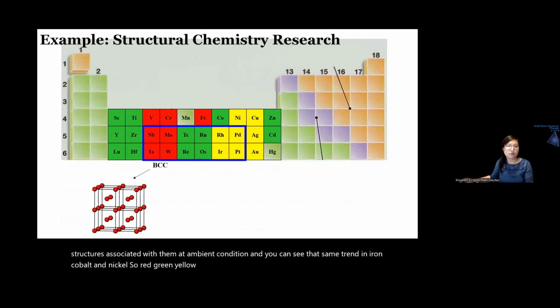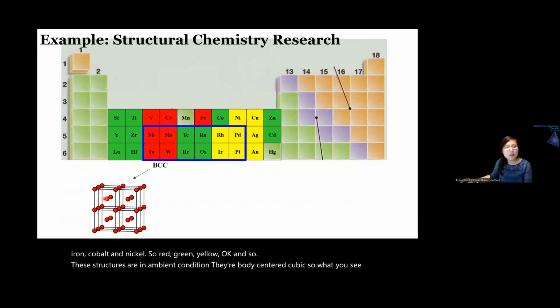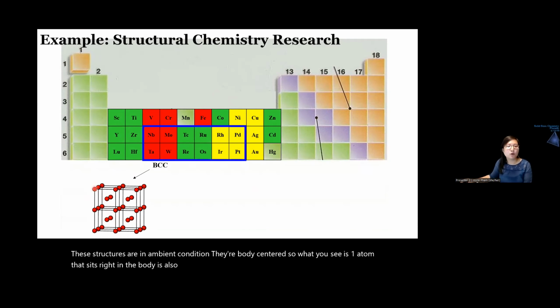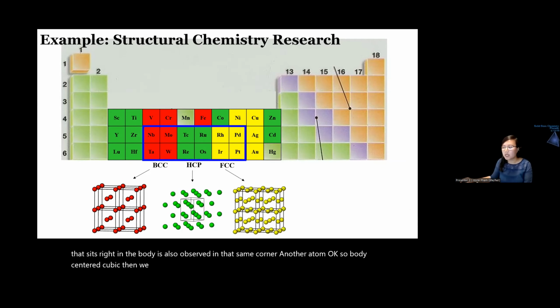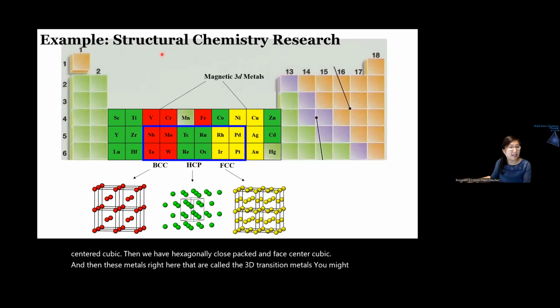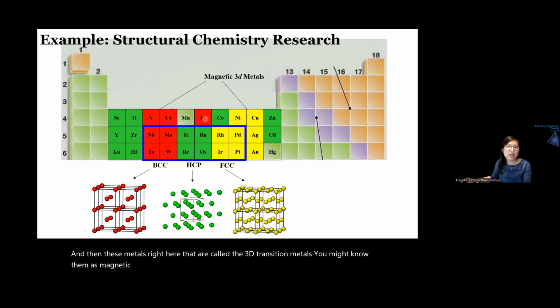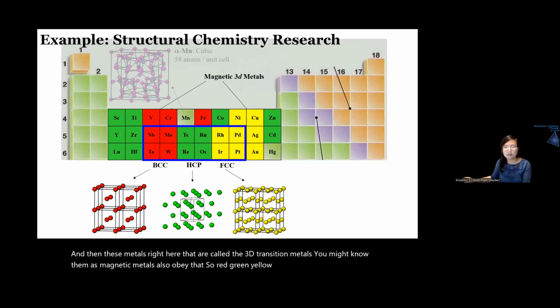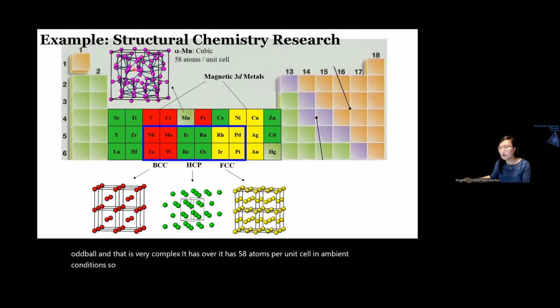And so these structures in ambient condition are body-centered cubic. So what you see is one atom that sits right in the body is also observed in that same corner, another atom, okay? So body-centered cubic. And we have hexagonally close packed and face-centered cubic. And then these metals right here that are called the 3D transition metals, you might know them as magnetic metals, also obey that. So red, green, yellow. But manganese is kind of an oddball, and that is very complex. It has 58 atoms per unit cell in ambient conditions. So my research group, at least for one of our projects now, really tries to understand the role of this manganese in the 3D transition metals.